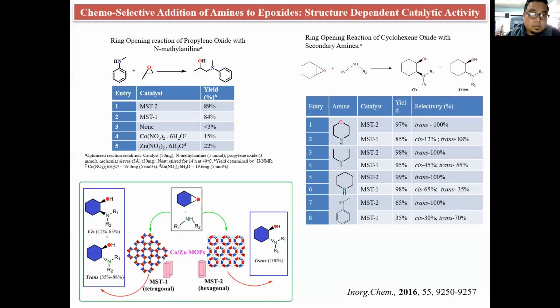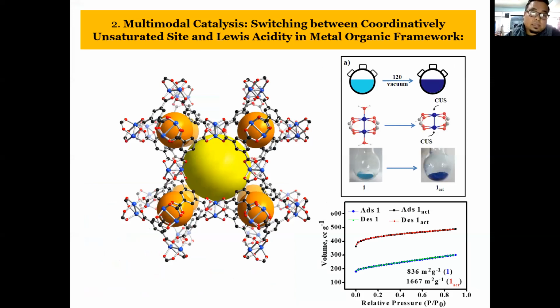Now the second example that we'll be showing is the multimodal catalytic attributes instituted by this metal organic framework. So we synthesized again the same HKUST1. I already told you about the coordination of these coppers, let's say this copper center generally has water molecules, and it looks turquoise, and this can be removed easily by activation. We can remove it by applying strong vacuum and high temperature, and they go out and we get a blue colored material. So the surface area also drastically changes. For the unactivated turquoise one, we have a surface area around 836 meters square per gram, whereas the activated one has almost double the surface area.